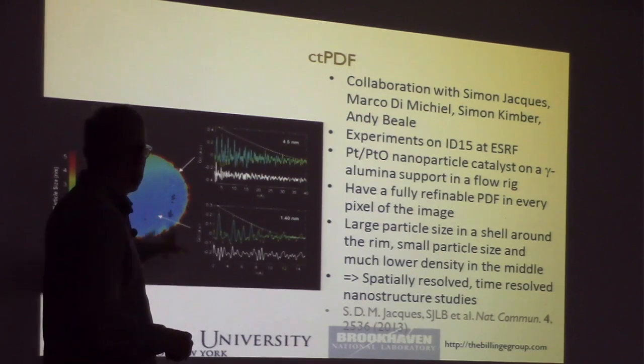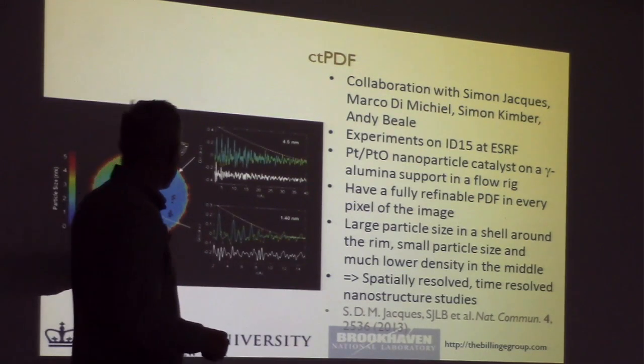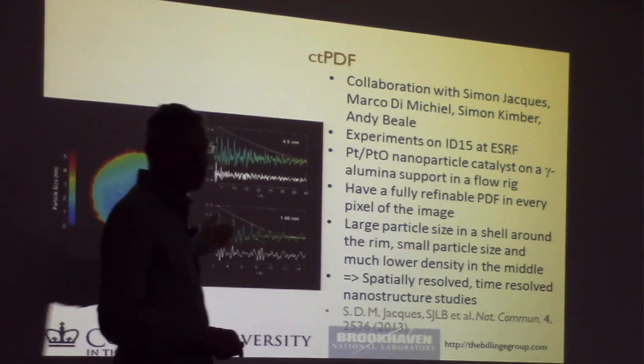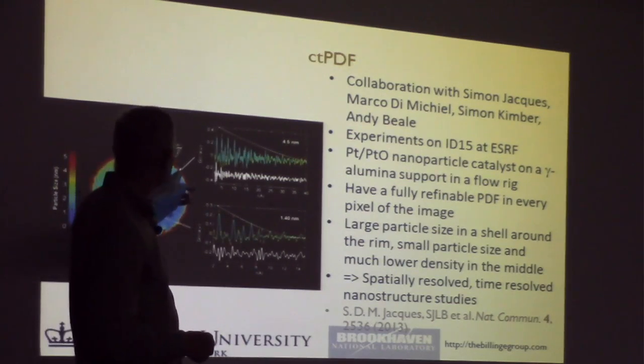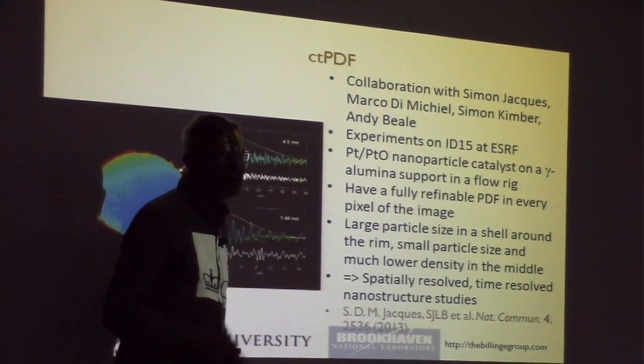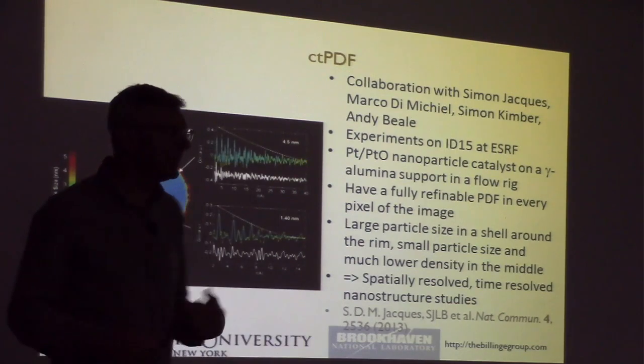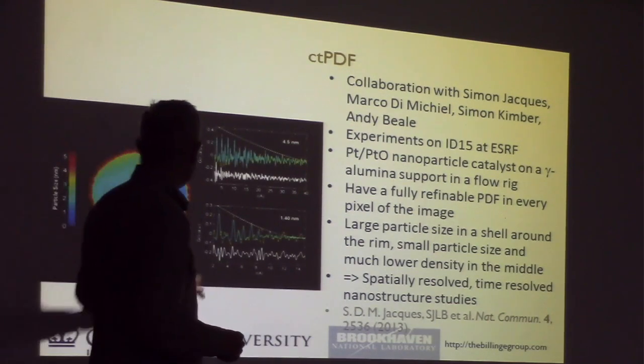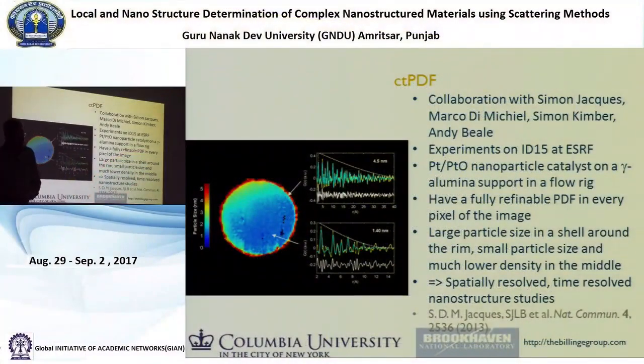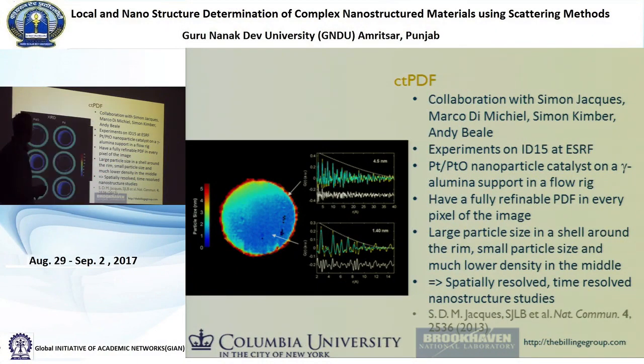But instead, this is a vector for us. We don't just have a single number in this pixel. We have a complete PDF inside that pixel. And inside this pixel, we have a complete PDF. So what we can do is we can actually fit the structural model to the PDF in that pixel. And so we can actually do a spatially resolved measurement of what the local structure is inside a bulk material like this. So it's pretty amazing.